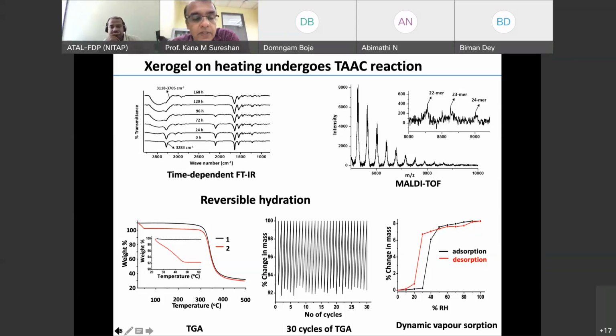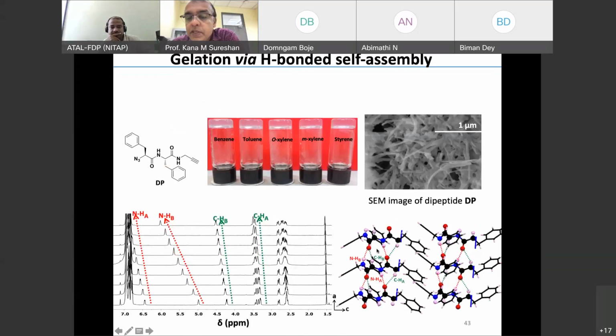Actually, what happens is, this is the crystal structure. We have seen that during the reaction, it takes water from the atmosphere to fill a void and form a hydrogen bond. And that water can be removed very easily because it's a hydrogen bond with a triazole nitrogen. At very low temperature, you can remove it. And again, after removing, you can keep the material outside and within no time, again, it will catch water. Again, you can remove it. So this can harvest water.